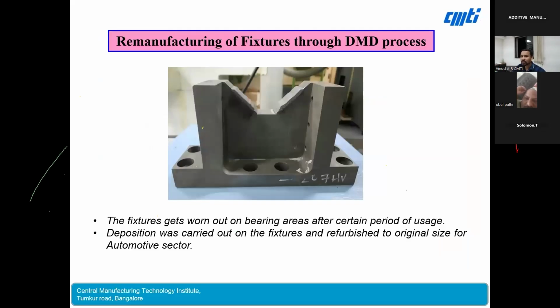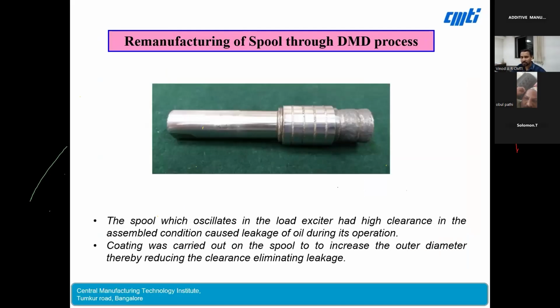This is a fixture which we did for Kirloskar Industries, a steel-based industry. Oscillating shaft remanufacturing we have done. Instead of throwing away the complete component, we are able to recover the part by coating and then machining. So it is like a hybrid approach. You can do the material addition by 3D printing process, and then you do the finishing by machining process.